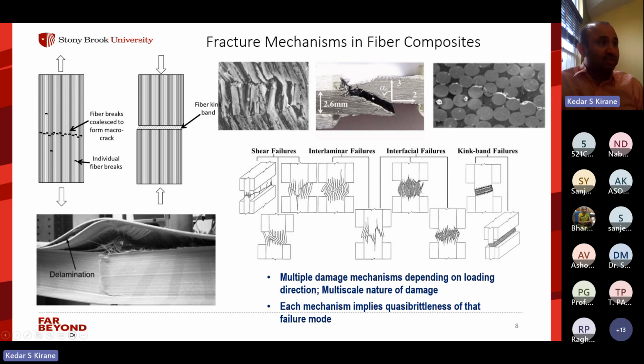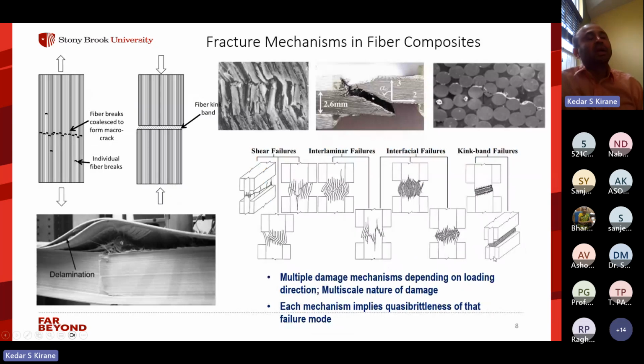Now, I should note that each of these mechanisms actually implies the quasi-brittleness that I was speaking of on the previous slide, that each of these mechanisms will probably be quasi-brittle and exhibit that kind of size effect in the nominal strength and also in the fracture toughness corresponding to that failure mechanism. So all said and done, one of the main failure mechanisms under compression is actually these fiber kink bands, and that is what I will mostly focus on today.